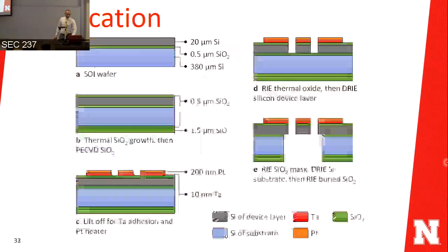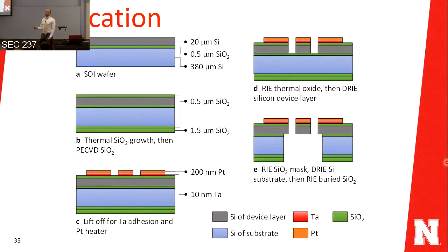So the fabrication of this device has been undertaken inside a clean room, and this began with a silicon-on-insulator wafer. That's the silicon layer, the device layer, with a 20 micron thickness of silicon that will comprise our final device. And the substrate is 380 microns. In between, there is an oxide which will work as an etch stop.